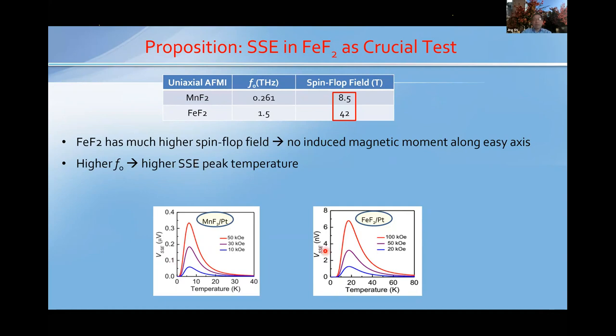Manganese fluoride has a peak temperature between 5 and 10 K, and iron fluoride has a peak at a higher temperature, in this case about 20 K also. So this is why we chose iron fluoride.